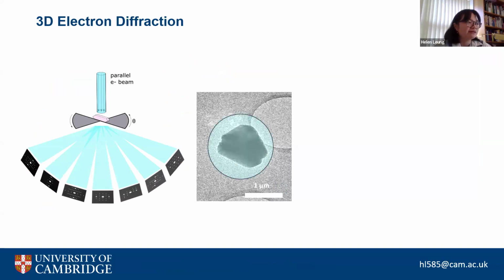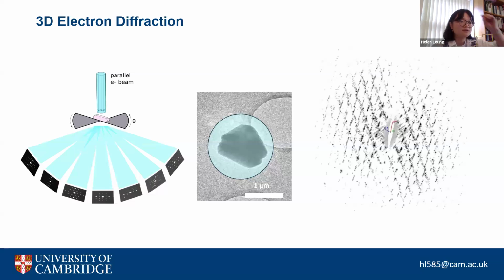What I want to remind everyone is that we're still illuminating a large area compared to 4D STEM, in 3D ED, because we have this parallel electron beam. And one of the things we noticed whilst collecting 3D ED data from xanthine was that some particles did not just have one reciprocal space lattice orientation. It appeared for lots of our particles that there was some interlocking going on between 2 reciprocal lattices. And so we suspected that this might be some form of planar disorder, or twinning specifically.